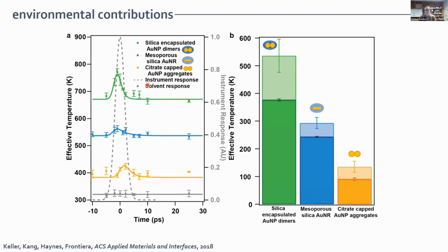Okay, we also tried to see how hot we could actually make these molecules on the ultrafast timescale. And so we explored different plasmonic materials, such as nanoparticles that are encapsulated in materials like silica. And what you can see from these transient spectra is that you can, in fact, make these molecules experience reasonably high vibrational kinetic energies, enough that would clearly impact chemical transformations.